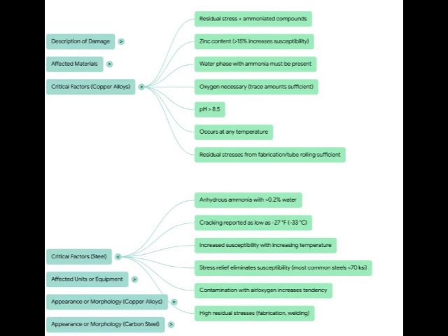Well, higher temperatures definitely make the cracks grow faster, no doubt. But lab tests have shown cracking happening as low as minus 27 degrees Fahrenheit. That's minus 33 Celsius. Whoa, so even refrigerated or cryogenic ammonia storage isn't safe? Nope, definitely not immune. And the failure point, if we connect this to the bigger picture, it's almost always near welds. Specifically, welds that haven't been properly stress relieved, and the areas right next to them, the heat-affected zones, or HAZs. Yeah, that whole zone around the weld holds onto that residual stress from the welding process. And the cracks almost always follow the grain boundaries in steel. It's overwhelmingly an intergranular failure.